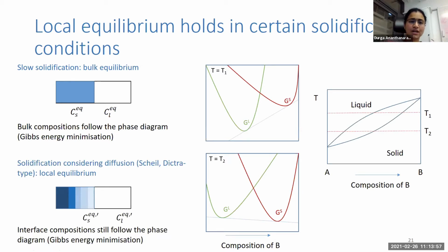But for this to happen, of course, we need very, very slow solidification, and that's not what happens in reality in any process for that matter. So we have to consider the effect of diffusion. There are several levels of approximation we can use here. One of the most popular ones is, of course, the Scheil solidification, where we assume that there is infinite diffusion in the liquid and absolutely no diffusion in the solid. And this is a fair approximation because typically the diffusion in solid is up to like 3 orders of magnitude or even more slower than in the liquid.